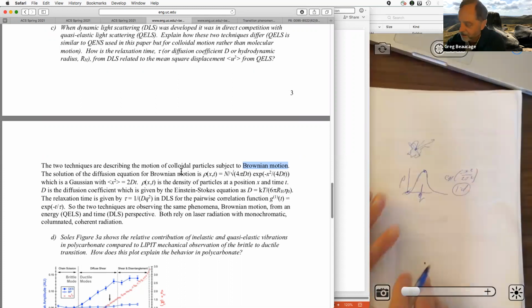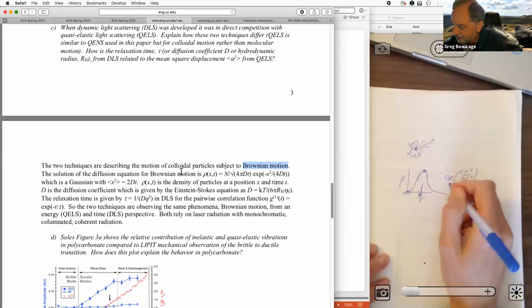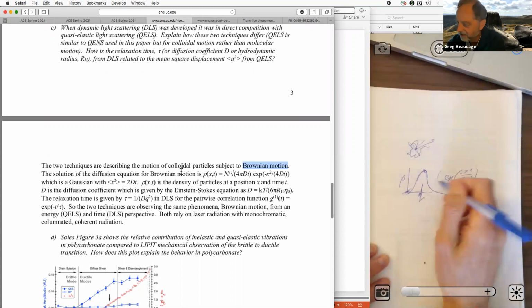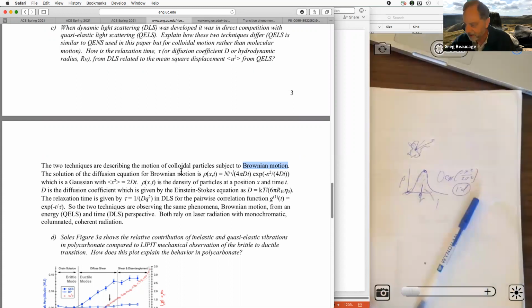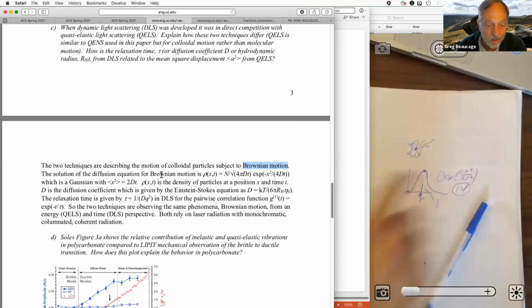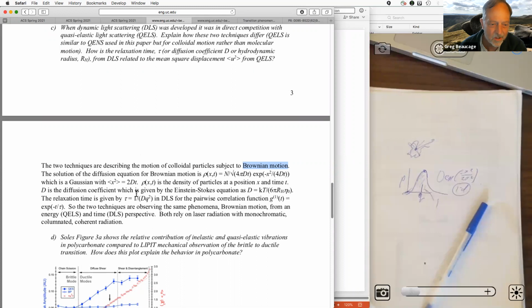Right? So in 3D, it's going to be that to the power of 3, because the 3 probabilities will be 3/2, right? And then there's some prefactor that normalizes it. So the integral of this thing is 1. So the total probability is 1. So you'll have a prefactor, which will be the integral of that. So anyway, that's what the prefactor is here. There's a bell-shaped curve, where 2Dt is the 2 sigma squared. Sigma squared is the mean displacement, which is the thing that you're measuring in the Brownian motion. And D is what you measure in the quasi-elastic measurement. In other words, in this equation, the relaxation time is 1 over Dq squared, so the correlation function is exponential minus t over tau, the relaxation time. And then you get the diffusion coefficient, and from the diffusion coefficient, you get the hydrodynamic radius.